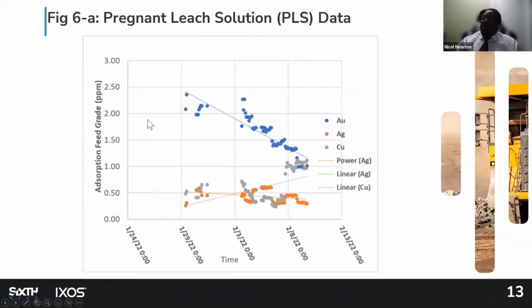Throughout the 145 hours that we ran, we did see a trend where the gold in solution was actually reducing throughout the period that we ran this test. We also noticed that the silver was virtually not really being absorbed, and then the copper value was also rather increasing in the leach solution.